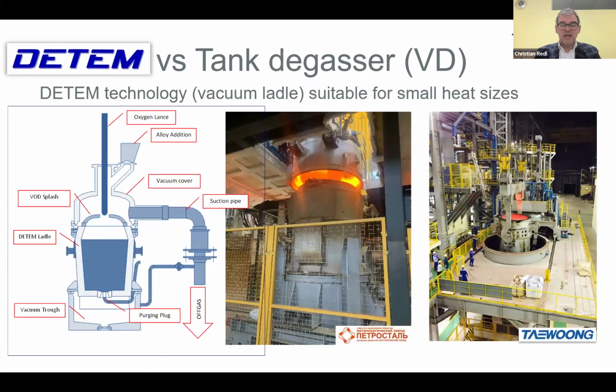There exist different types of ladle treatments. The first one, shown on the left side, is the DETEM concept, the vacuum ladle, where you do not have a tank, but you simply seal the ladle, which has a special flange, by a vacuum cover, and you're evacuating only this very small volume. This is usually recommended for very small heat sizes, typically for small scale steel plants dealing with heat sizes up to 20 tons. You have lower heat losses during the treatment and a low volume which you have to evacuate, so the vacuum pumps can also be designed in a smaller size.